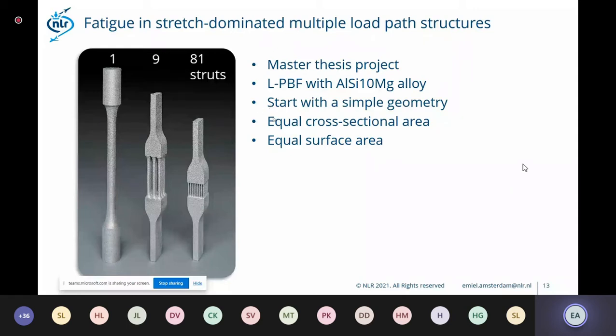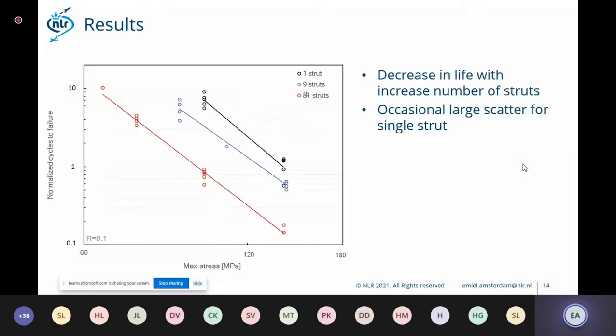So we tested these in fatigue, and these are the results. Here you can see the normalized cycles to failure. We normalized all the results by the average of the single struts at 140 megapascal maximum stress. These are the results: the number of cycles to failure on the vertical axis, and the maximum stress on the horizontal axis. As the maximum stress increases, the number of cycles to failure go down, as expected.